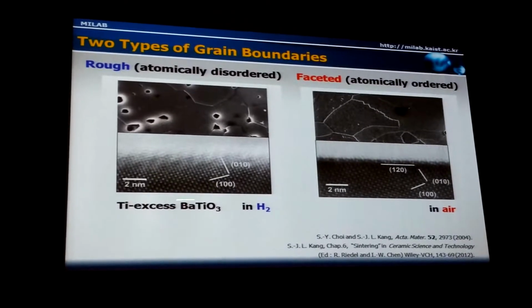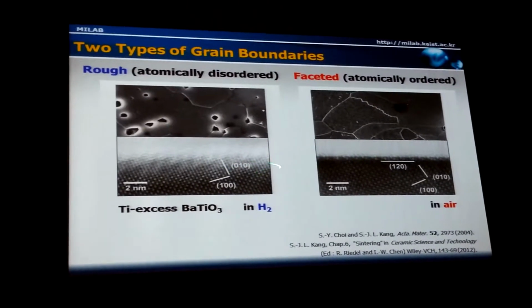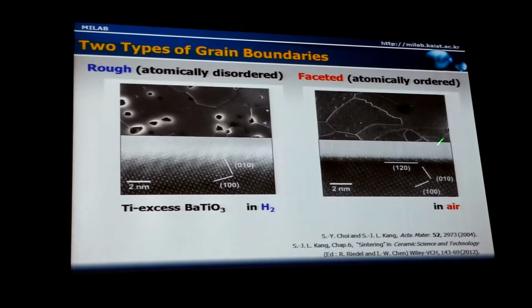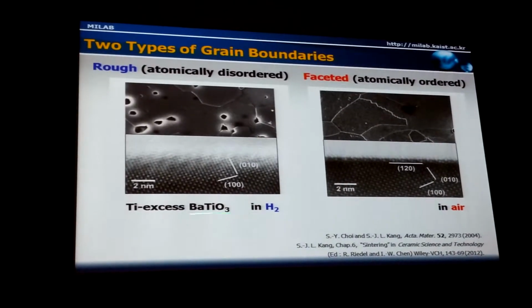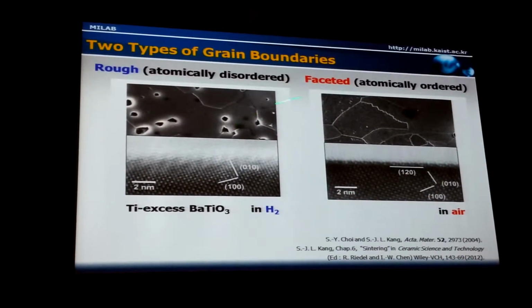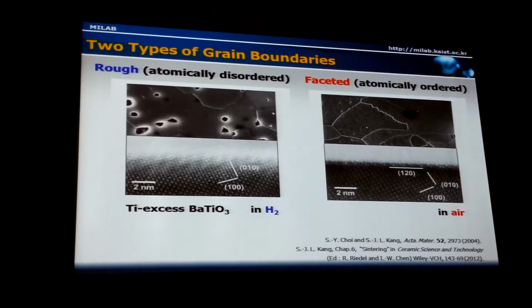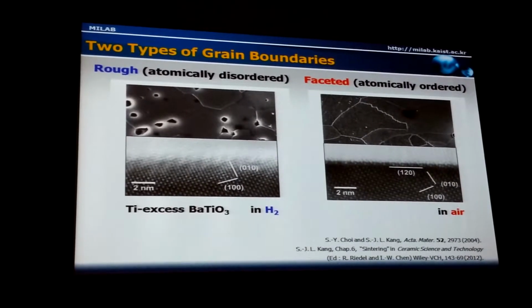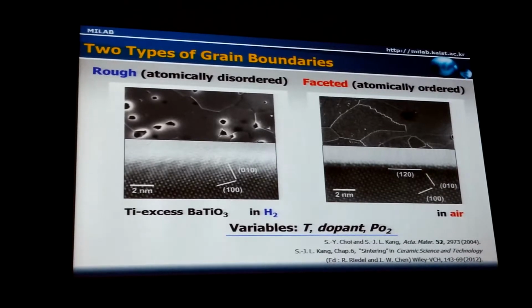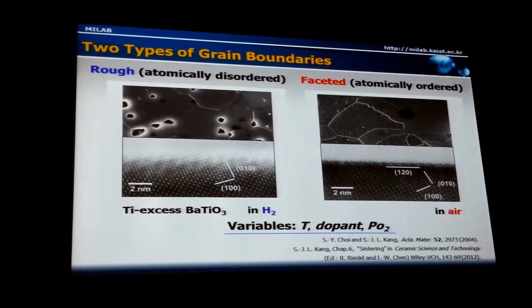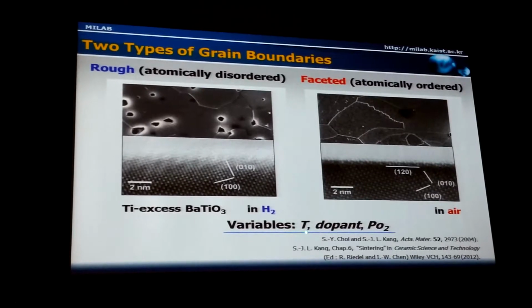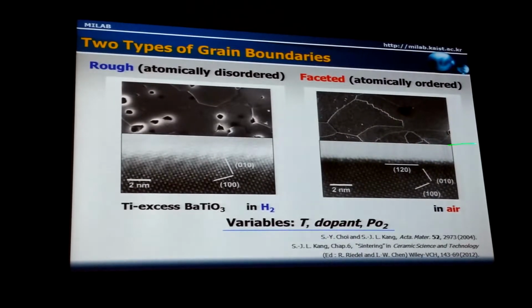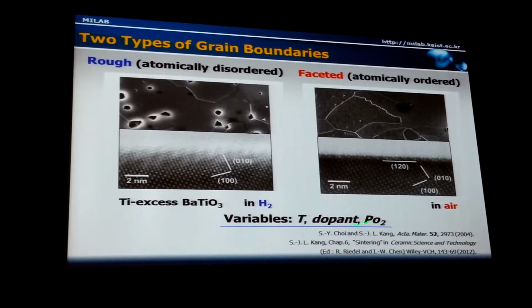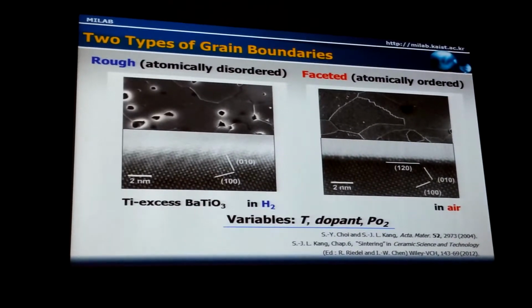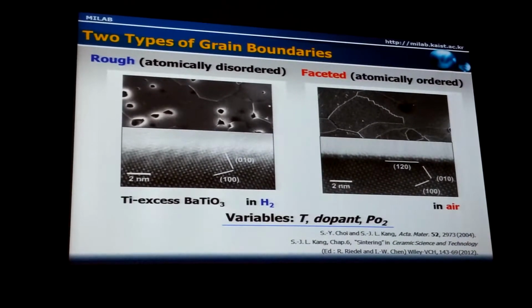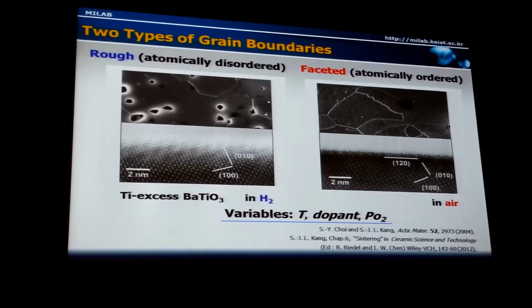And as this example shows, the boundary type can be controlled by simply changing the oxygen partial pressure, in this case barium titanate, in hydrogen or in air. So we can make the boundary faceted or rough by changing oxygen partial pressure in the case of barium titanate. But we can also change the grain boundary structure by adding dopant or changing temperature. And what will happen when the grain boundary is atomically ordered?